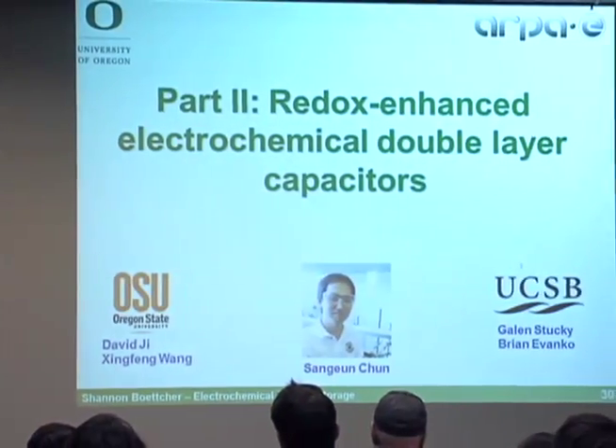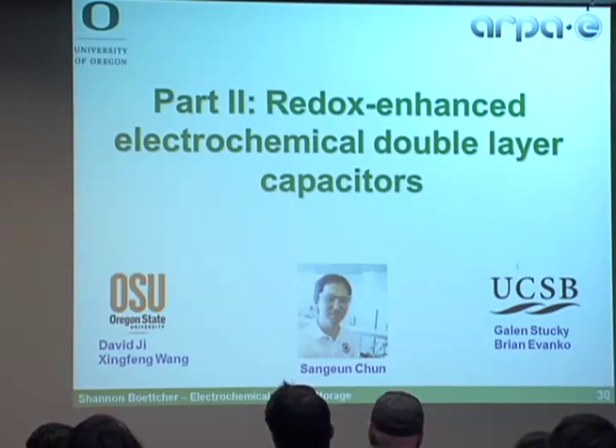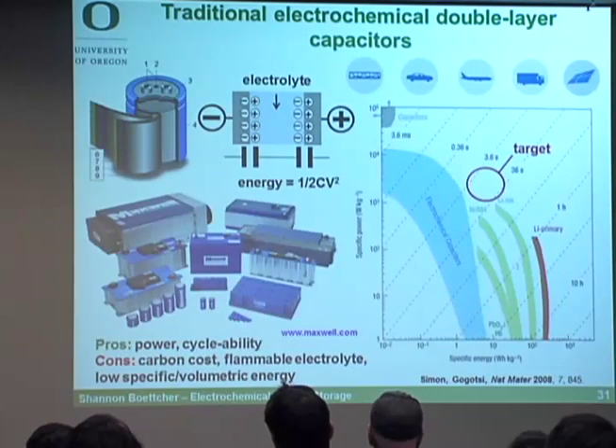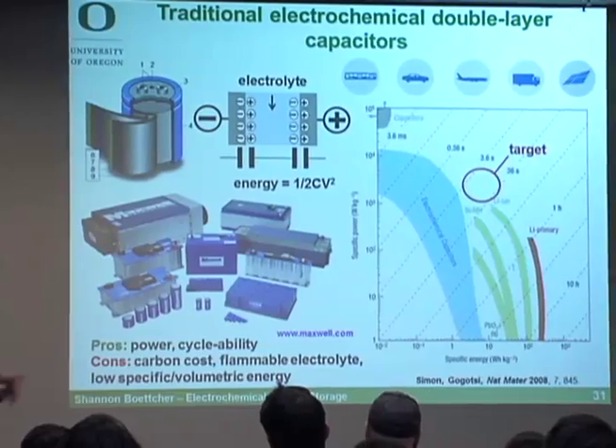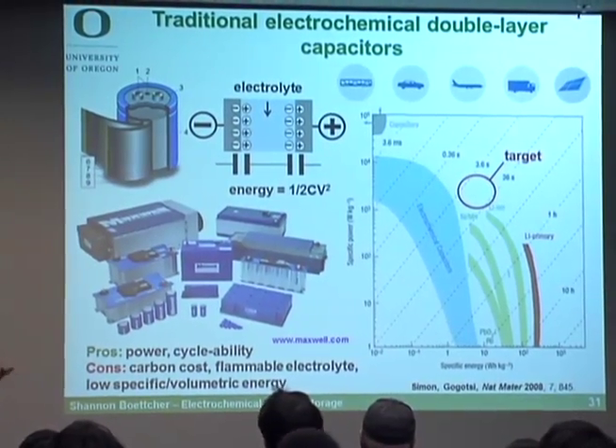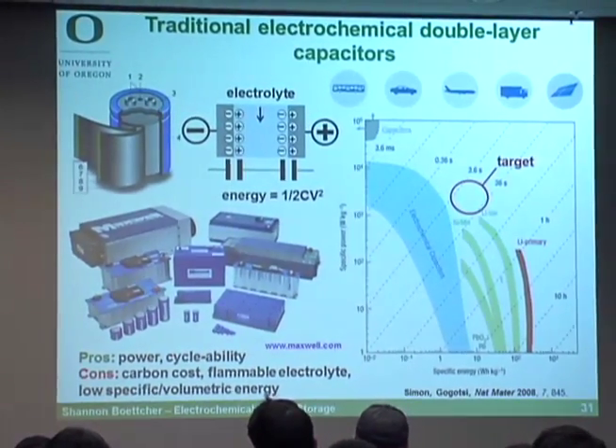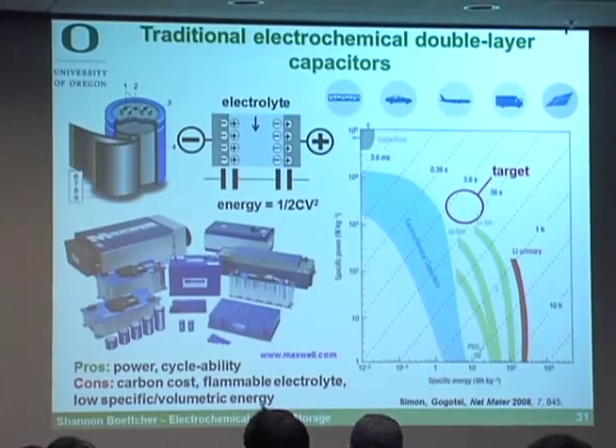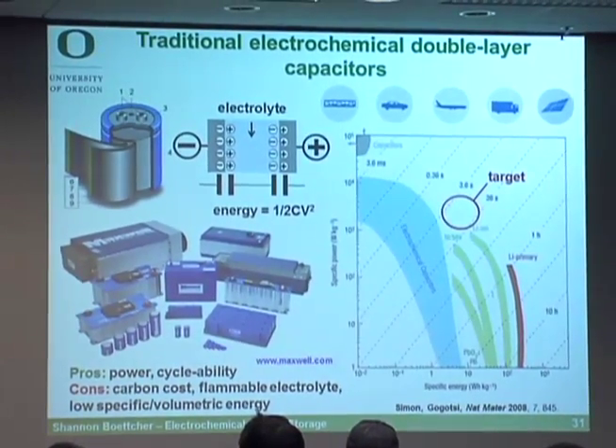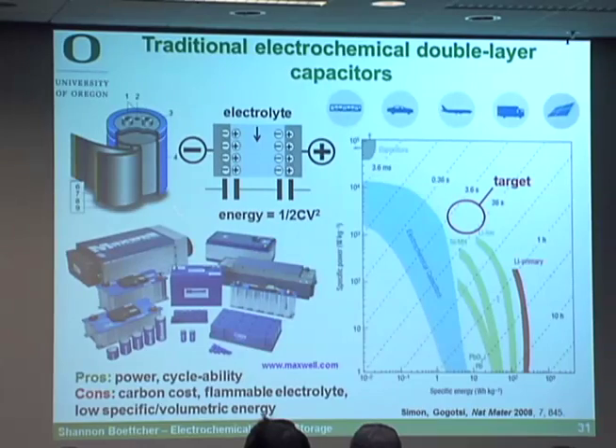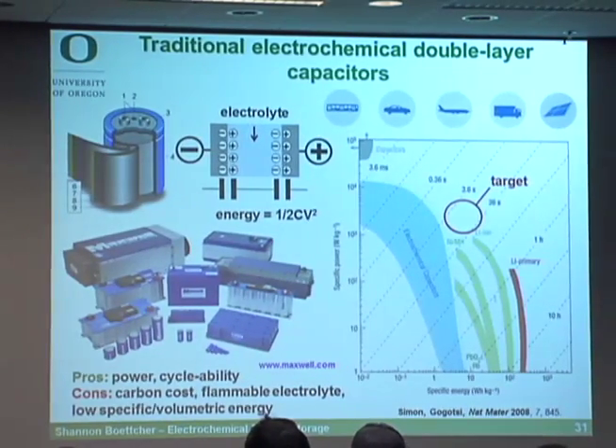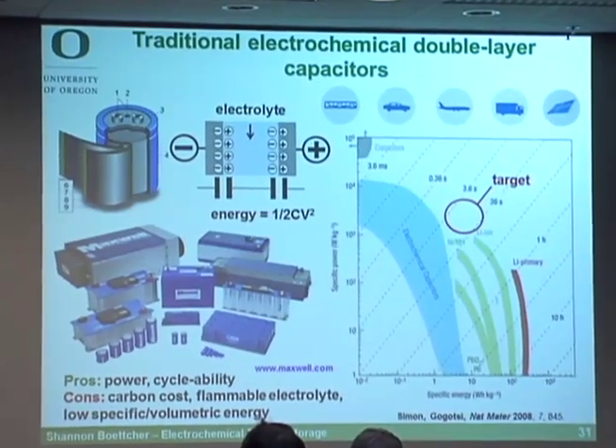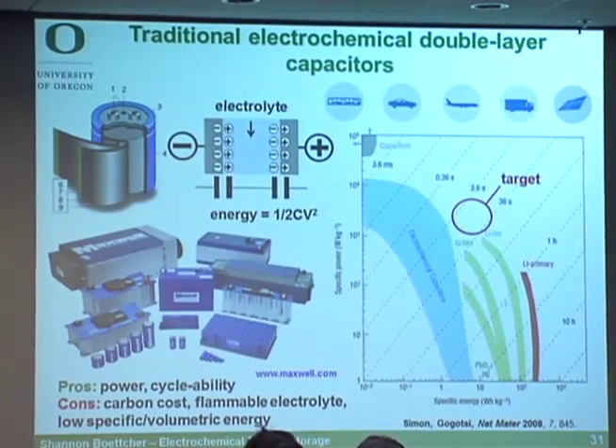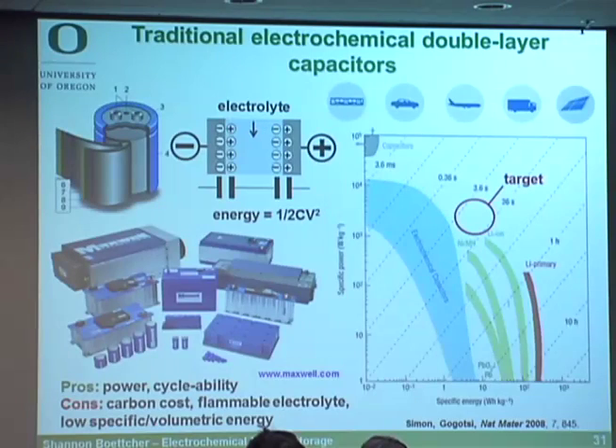The idea is that we want to make an electrochemical double-layer capacitor that has an enhanced capacity due to some Faradaic, some redox process that we want to control. A traditional electrochemical double-layer capacitor is basically two high surface area porous carbon electrodes separated by a separator. They're on aluminum foil electrodes. When you polarize them, you make a double layer at the carbon electrolyte interface. It's usually a non-aqueous electrolyte. And in that double layer there's an electric field, which stores energy.